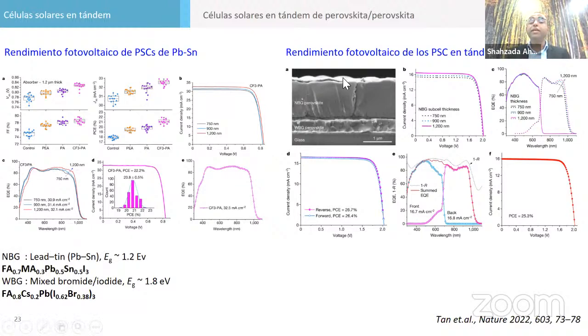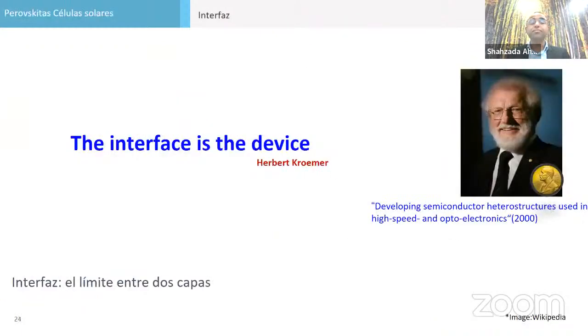They varied different thicknesses here, and for the narrow band gap perovskite you can see they go up to 1,200 nanometers thickness. This is a large area they fabricated, what they call 1 square centimeter, 2 square centimeter, which gives you 22.5% efficiency. There is a company called Oxford PV working on silicon and perovskite tandem, which is also close to 30% efficiency. They have reported it.